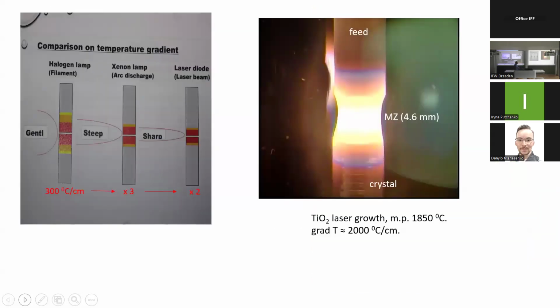And the main advantage of the laser heating is the temperature gradient in a hot zone. If we compare with halogen lamp, the typical temperature gradient is about 300 degrees per centimeter. If we use arc lamp, we get around 900, and with laser up to 2000. And here is a real growth experiment that we performed last week with CO2 laser growth. The melting point of this material is about 1850 degrees. The zone is relatively short, for this melting point it's just 4.6 millimeters in length.